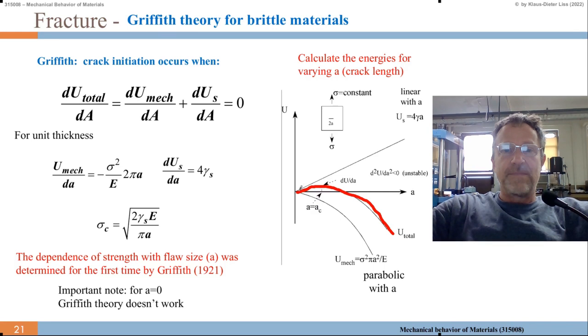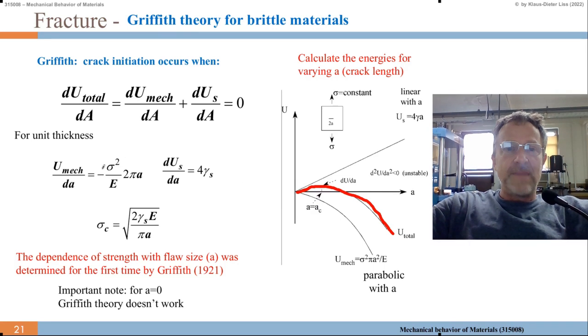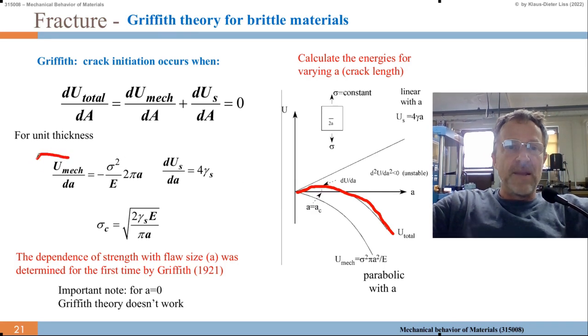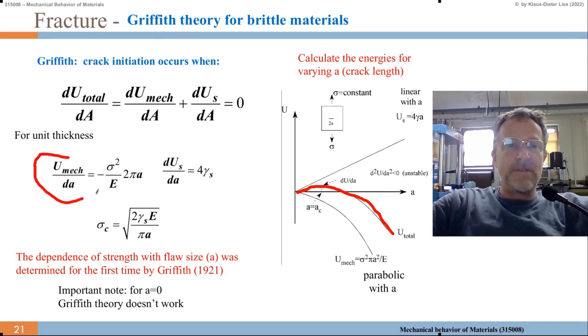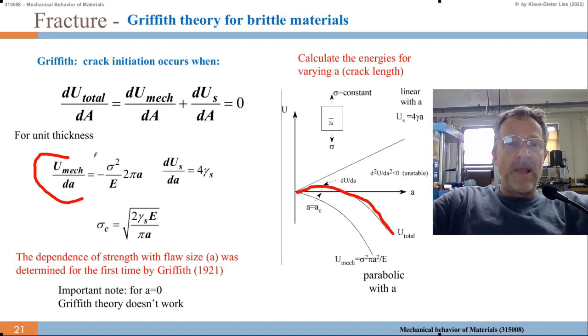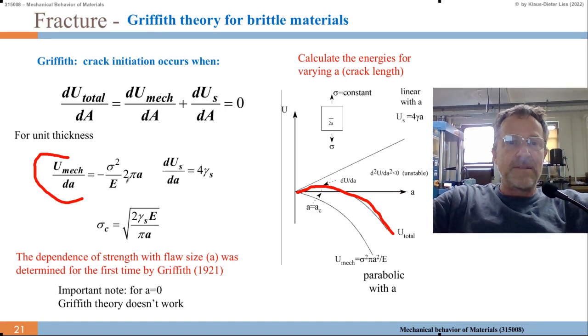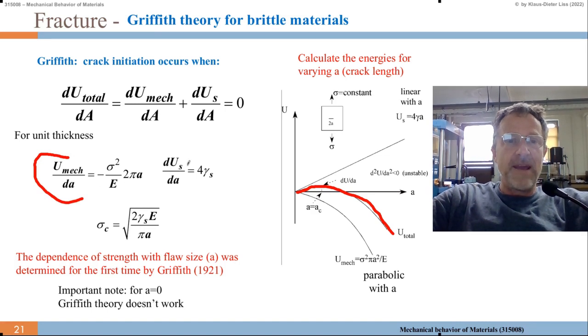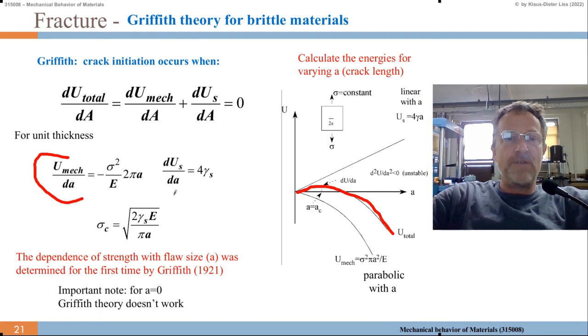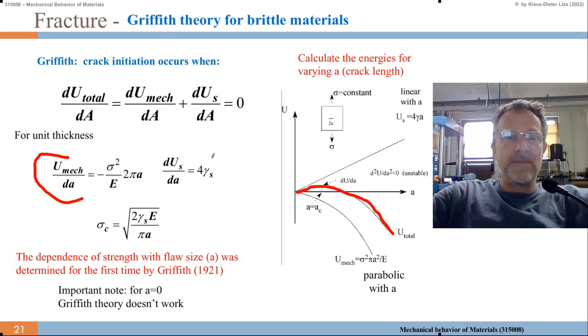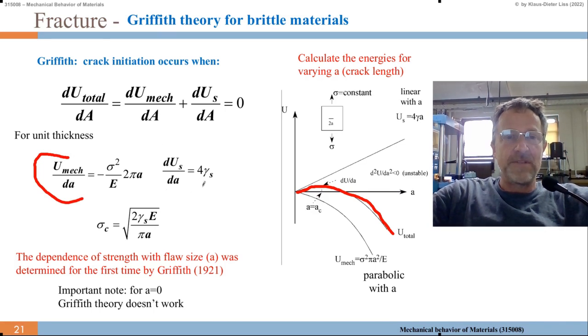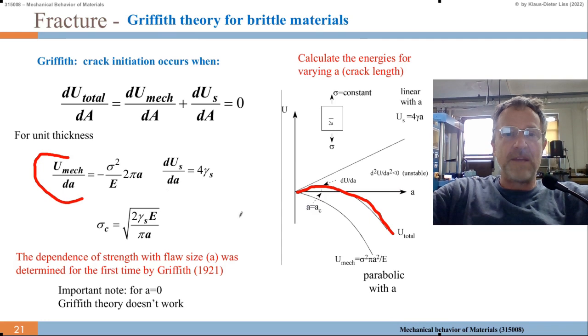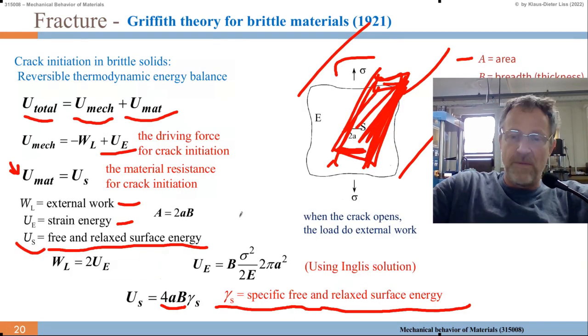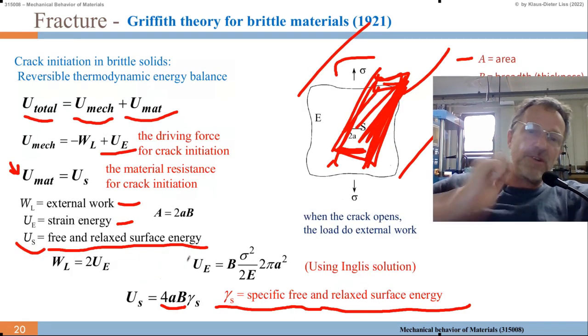We have these two terms. So dU mechanical over dA equals minus sigma squared over E times 2 pi a, and we have dUS over dA, the surface energy, equals 4 times gamma S from the formula here. So US and UE.